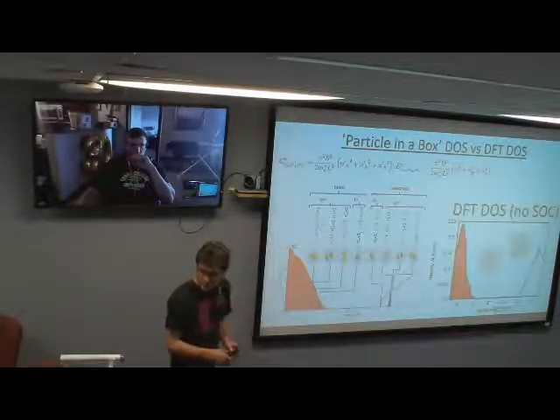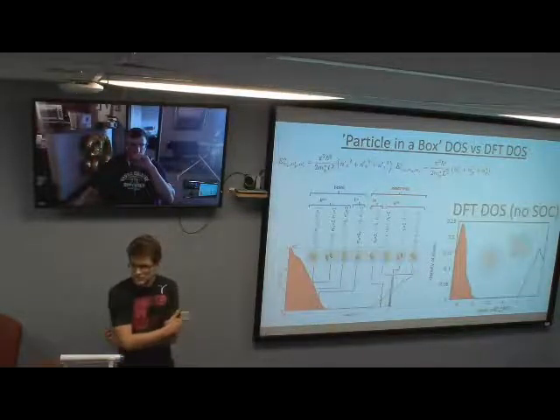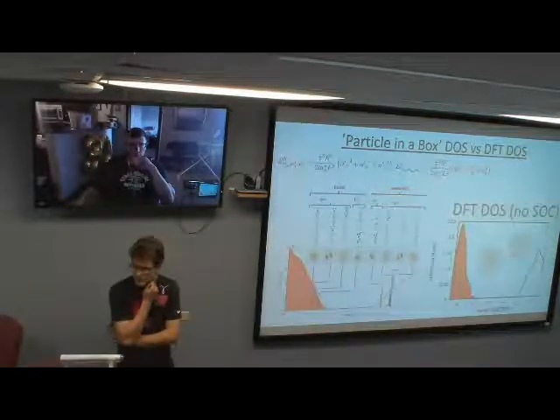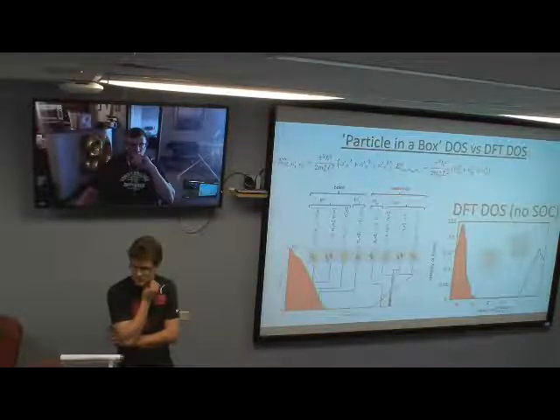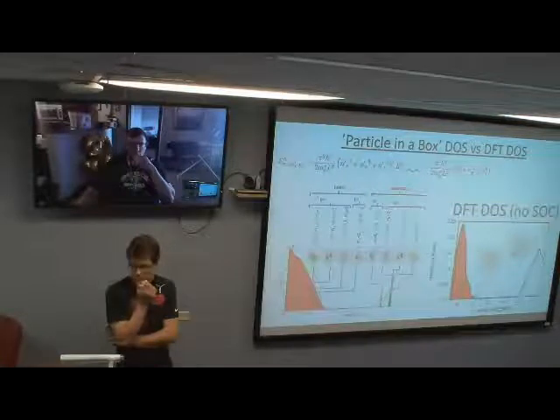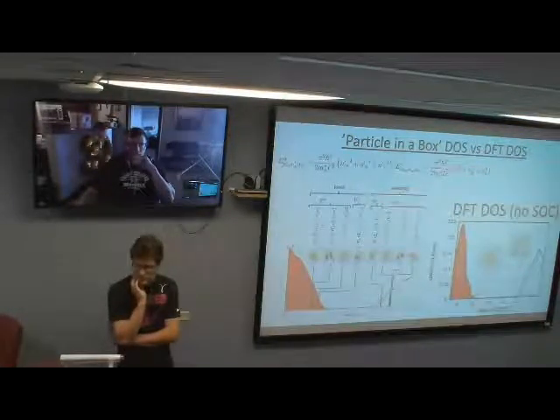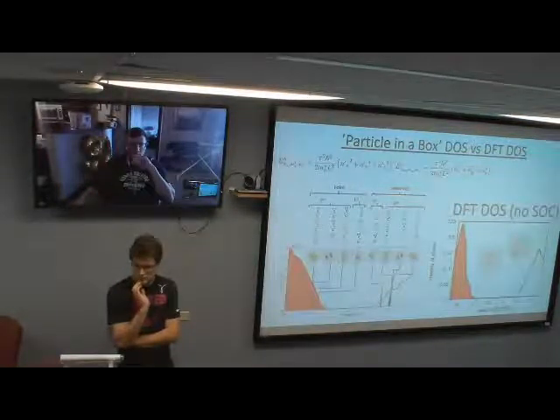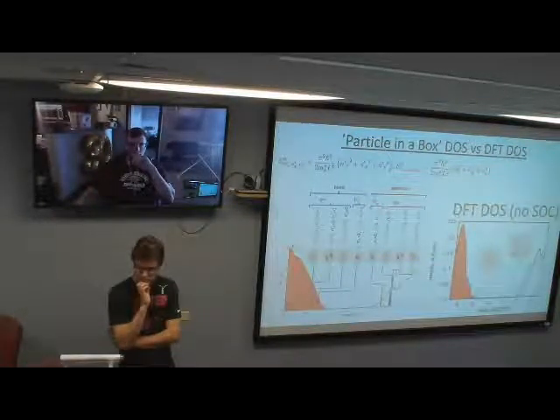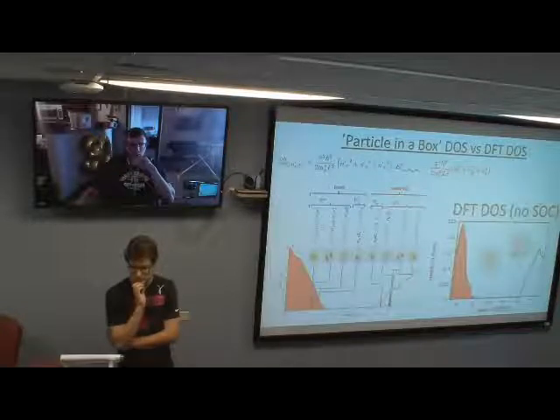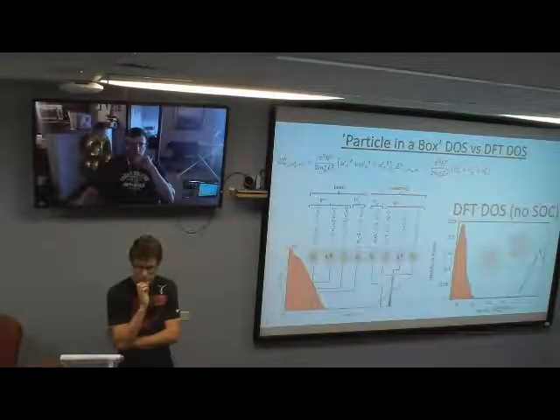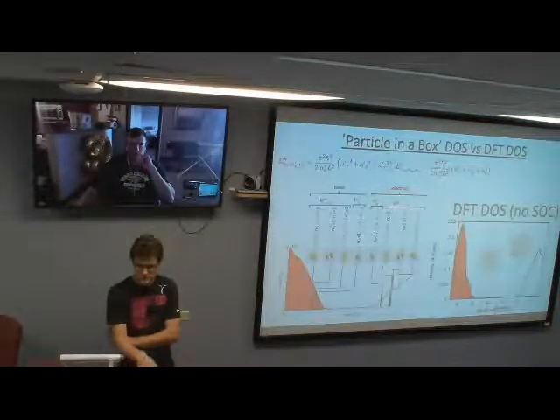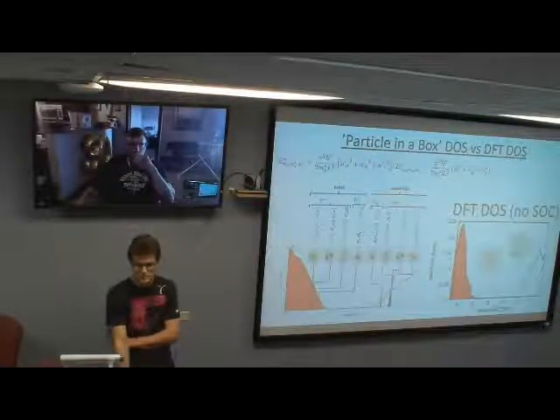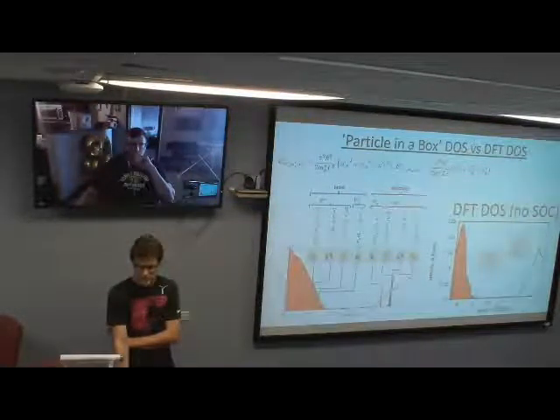No, it will not fix it. The suggestion was to use the solution for the finite box, finite depth or finite height of the wells. You don't need to immediately rush and do the calculations. But if you compare and see any discrepancy, you can blame the absence of the finite height of the wells. You can just open books and see what the solution would be for the finite box, and of course the solution will depend very strongly on your potential and the energy of the levels.